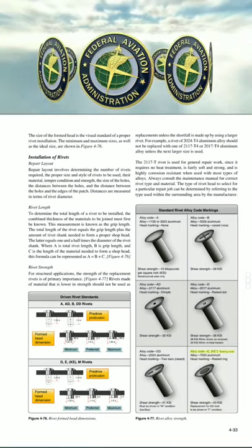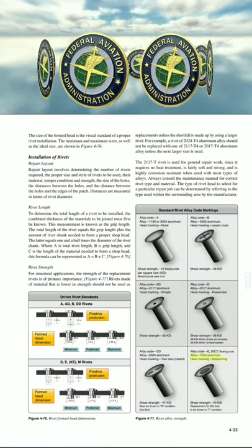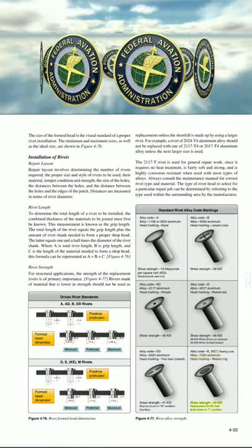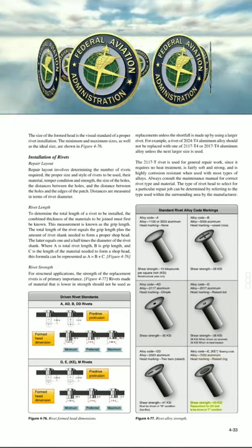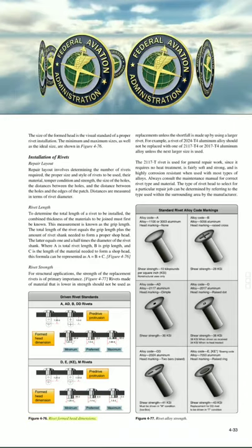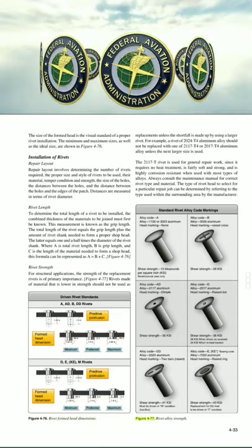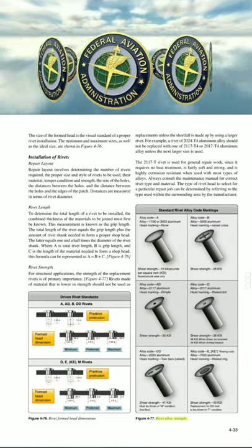Alloy code E, key asterisk asterisk Boeing code. Alloy 7050 aluminum, head marking raised ring. Shear strength 43 KSI, replacement for DD rivet, to be driven in T condition. Figure 4-76. Rivet formed head dimensions. Figure 4-77. Rivet alloy strength.